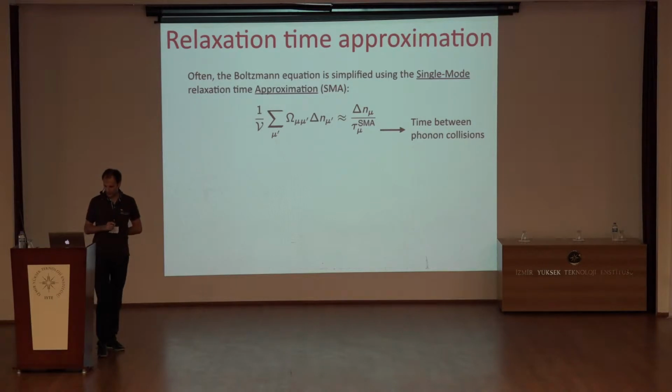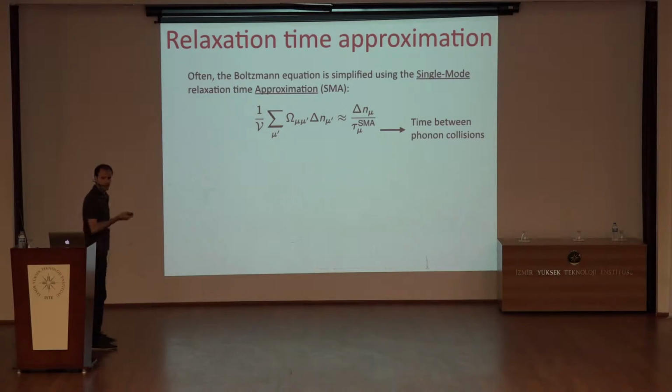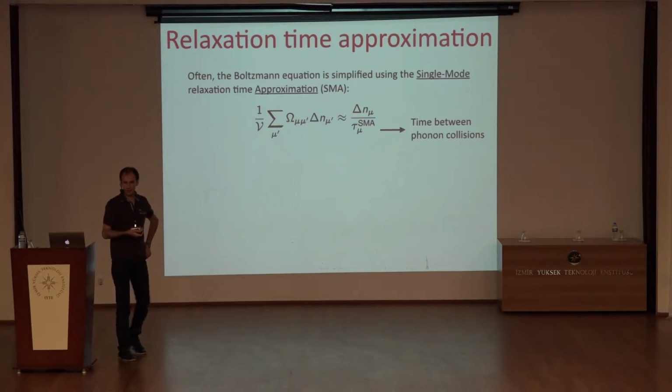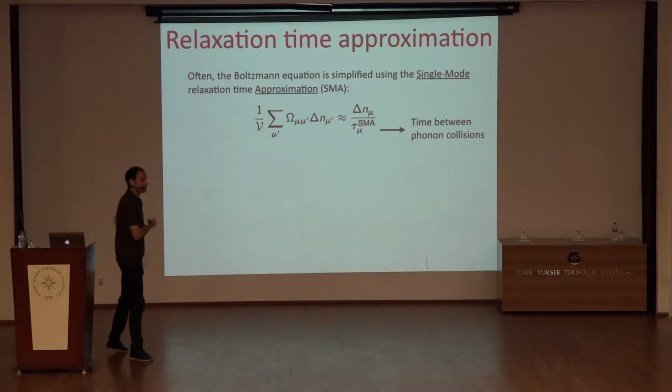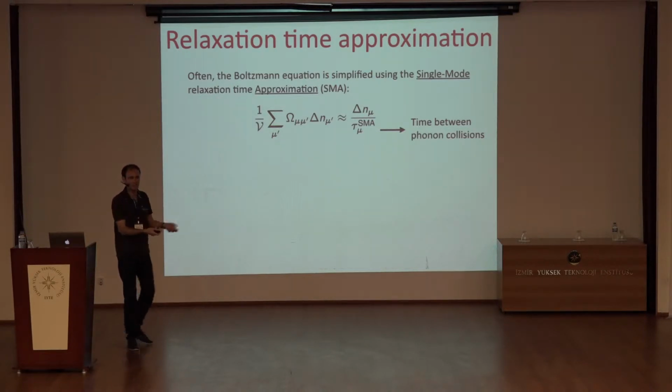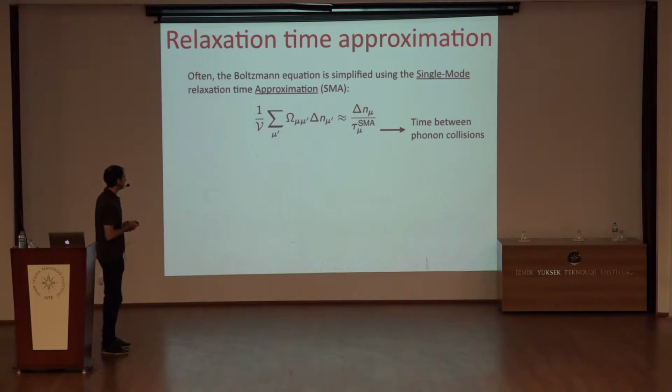Okay, so now going into the more interesting part of the work, let's recall again the relaxation time approximation, which we have seen appearing today and yesterday. Mathematically, the main reason you want to introduce this expression is that the complete expression of the scattering matrix is too complex. So you want to simplify it, and basically you drop the off-diagonal matrix elements. Of course, one integral goes away, and you have something much simpler to deal with. So simplicity is the reason why you introduce this approximation.